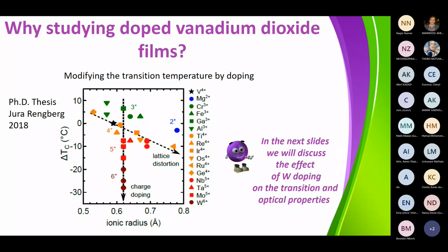But you can also play with other ions. And if you modify the ionic radius, you can still decrease the transition temperature by putting larger ions with larger ionic radii, or you can increase the transition temperature by putting ions which have a smaller ionic radius. Okay, so in the following of this presentation, we are going to focus on the tungsten 6+ doping agent, because this is one of the most efficient ones to reduce the transition temperature.